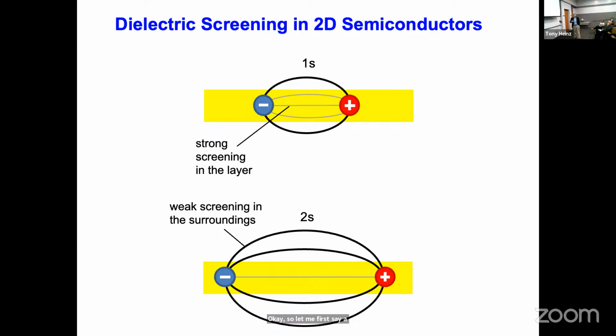This is the highly simplified picture of the excitonic states, the ground 1s state and the 2s state. The notion is this is roughly the scale: the exciton is about a nanometer or so, as we were just discussing, 1.5 nanometers. The thickness of this medium is something like 0.5 nanometer. So in the ground state, you can already understand that there's fundamentally no way to decouple the excitations from the external environment.